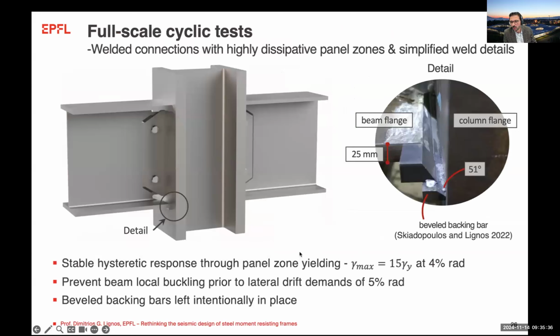And with that, we went on to conduct tests where we wanted to construct a beam-to-column connection the way we do today, but we wanted to achieve stable hysteretic behavior through an alternative dissipative mechanism, which is yielding in the panel zone. At 4% drift, we would like to have at least 15 gamma Y in the panel zone, so highly dissipative. We want to prevent beam local buckling prior to a lateral drift of 5%, so that A, we can minimize repairs in the beams in the case of modest drifts, and B, we could alleviate or delay instabilities, so that would naturally increase the capacity of the system against structural collapse.